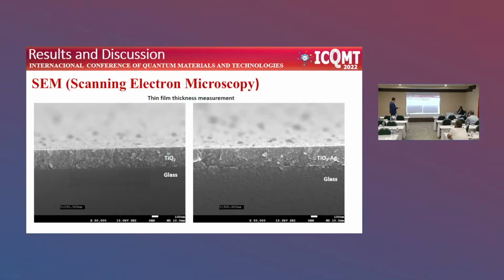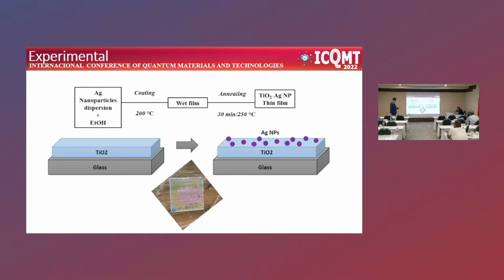Well, as you can see, the thin films are totally dense, no cracks are there, so the thin films are really applicable for this type. In other applications, you can see very clearly the density of the thin films. Well, the thickness is around 300 nanometers. It's difficult to obtain the same thickness in all the samples because it's a handmade method, but we can try to obtain regularity in this thickness.